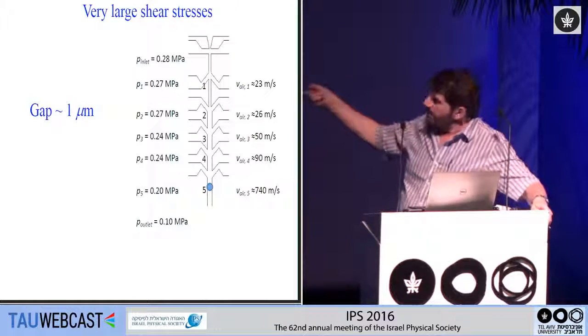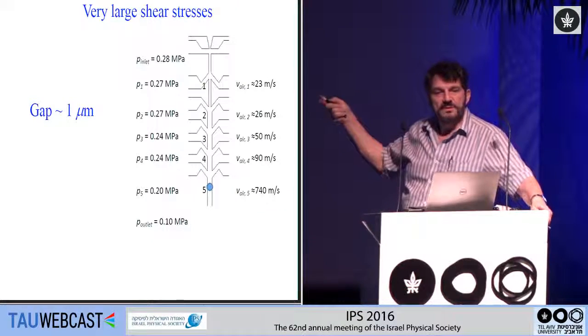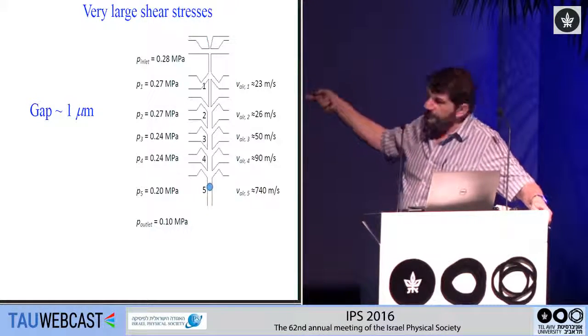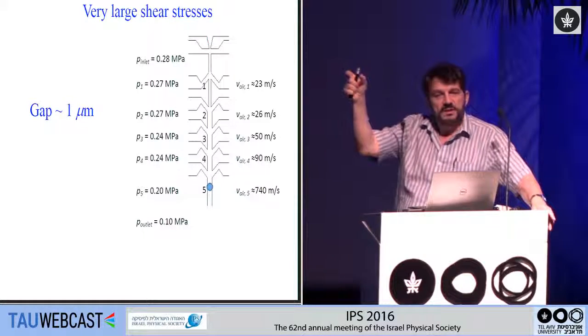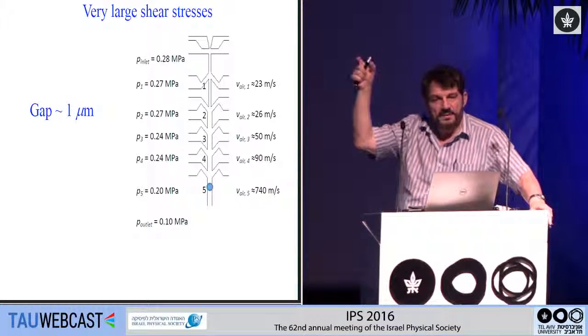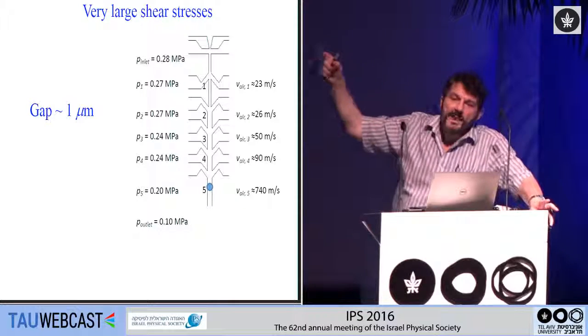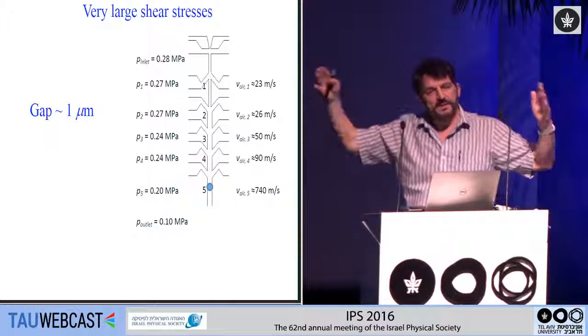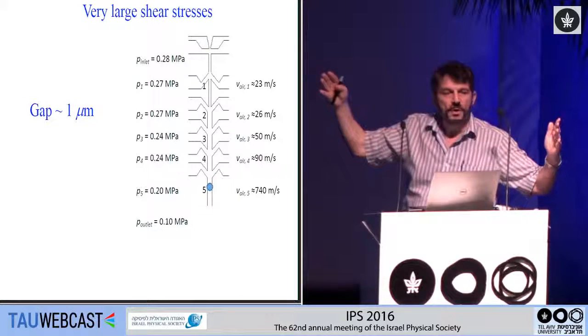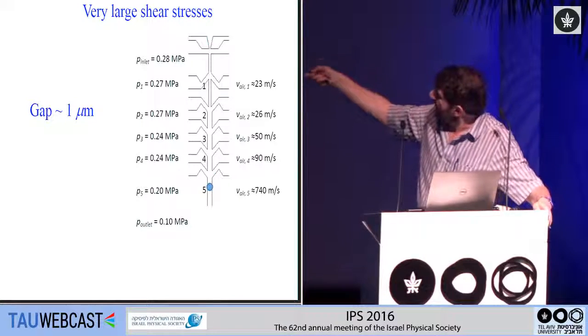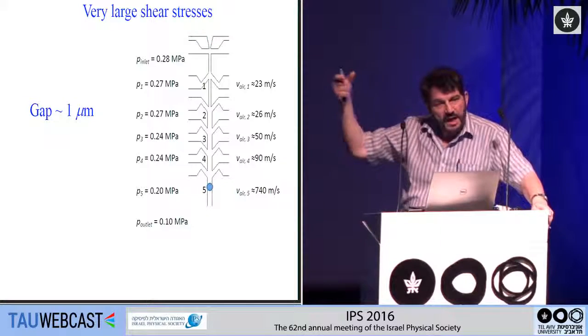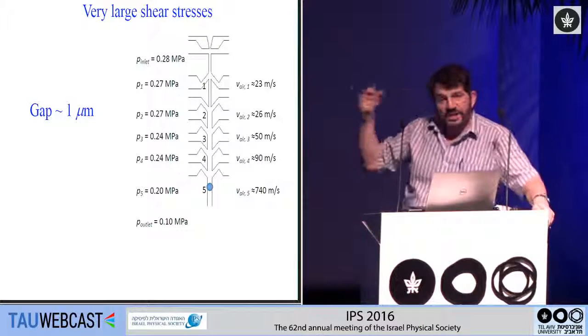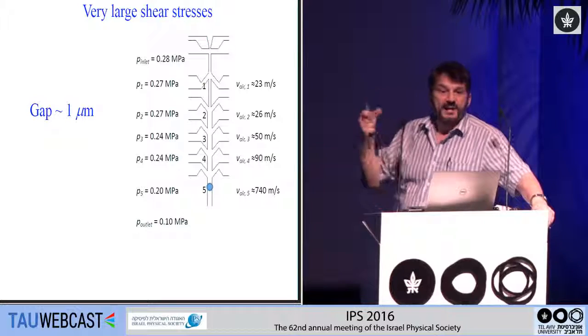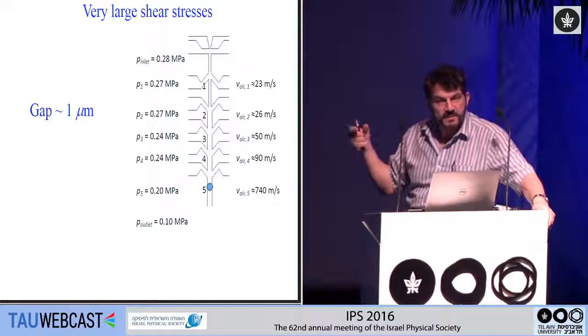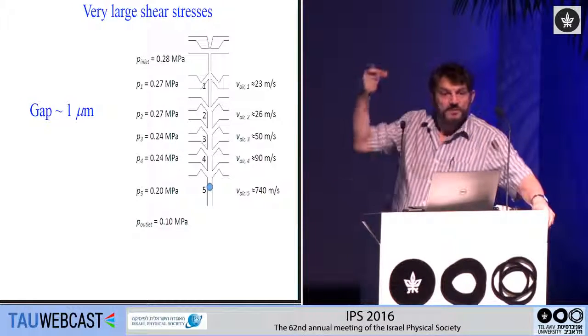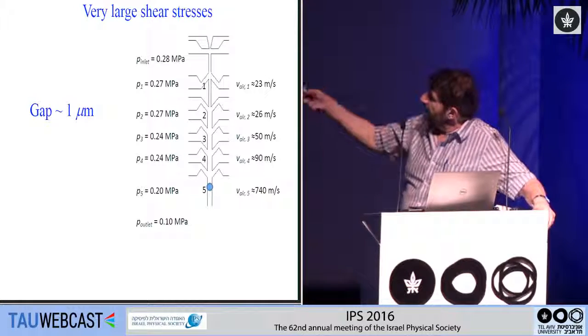But look, the drop has essentially the same diameter as the channel. You can measure the difference, in fact, just by taking an image and looking at the videos. You can say, well, maybe there's a gap between the channel and the drop of about a micron. So you're forcing the air around the particle through a gap of a micron, and the air is moving a factor of 10 on average, a factor of 10 faster than the particle. So of course you're accelerating the particle, but you're also blowing the air by very, very rapidly.